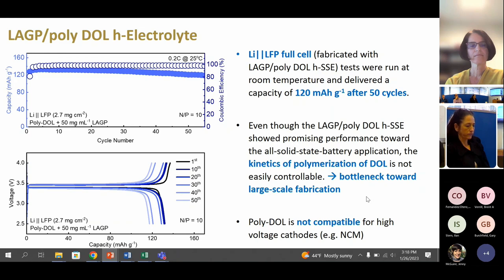Similarly, we transitioned from what's called a half cell test to a full cell, and we see a high coulombic efficiency of nearly 100%, which is essentially retention between the cycles. Similarly, the capacity is quite high as well after the 50 cycles.